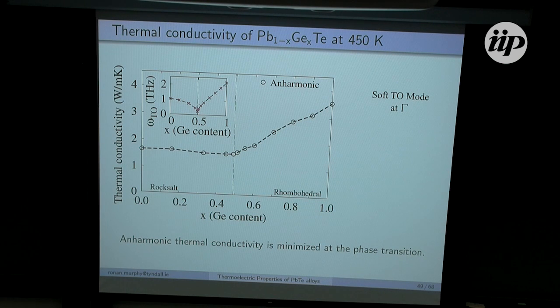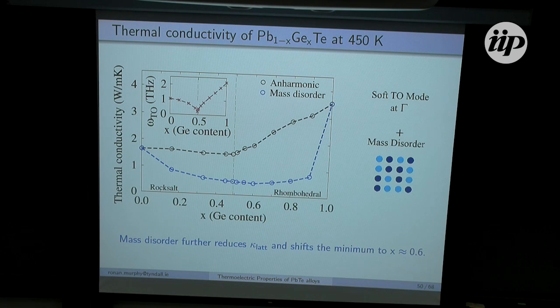So now I just want to take a bit of a moment to go back, and this is the slide I showed you previously. Now what we want to do is take into account mass disorder. So in doing that, we get this blue curve here, which is the thermal conductivity due to mass disorder and anharmonic processes. And we see that we get quite a substantial reduction to the thermal conductivity, again combining these two effects of the softening of the TO mode, increasing the TO acoustic interaction, and the effects of mass disorder.